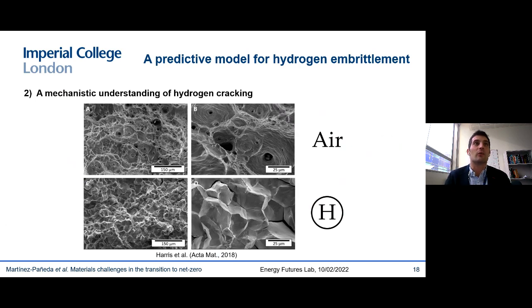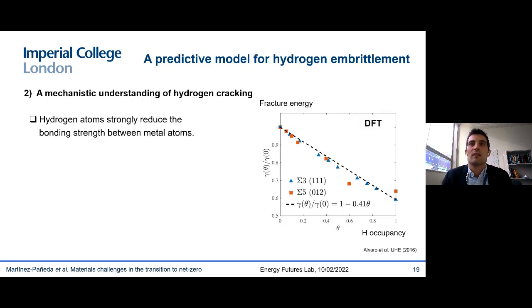That takes me to the second ingredient. So this is the mechanistic understanding of hydrogen cracking. And here the key question to answer is, how can it be that the same material in air shows a ductile fracture process, so it fails in a ductile manner with these microvoids nucleating, growing, and coalescing and so on, but if I put the same material in a hydrogen-containing environment, I see these brittle fracture patterns where you see cracks opening along the grain boundaries. And in my opinion, there are three key ingredients to understand why this is happening.